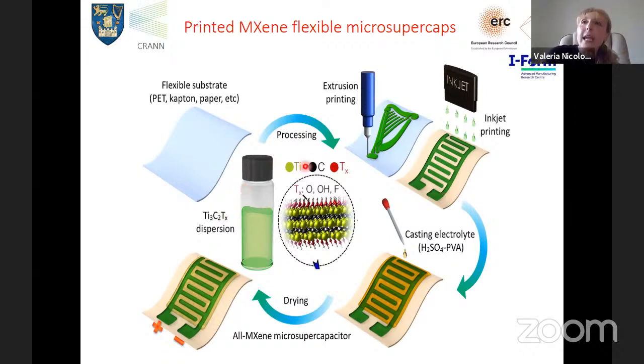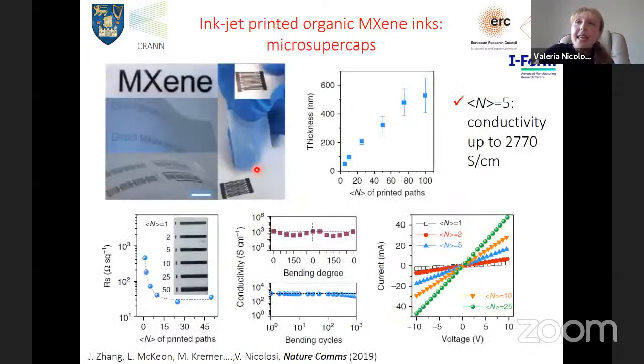And indeed, we developed methods of loading these inks in our printers, and we could start engineering complex devices by either extrusion printing or inkjet printing. And these are the devices I'm going to show you. So we really loaded these inks in our printers, printed our devices, cast the electrolyte on top of them, printed another layer of device on top, and then really tested them as devices. This is an example of some devices that we printed.